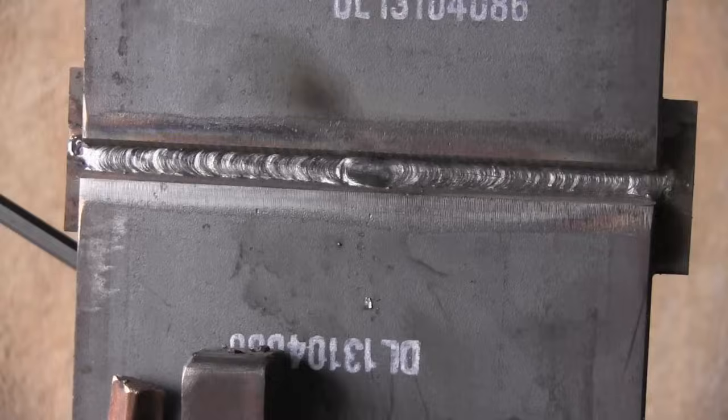I'll show you that in just a second. Again, we're about 135 amps with a one-eighth 7018 Lincoln Excalibur rod. I'm tying in to where that crater of the previous run and then I'll fill that crater in here briefly and then come out. That's what that looks like.